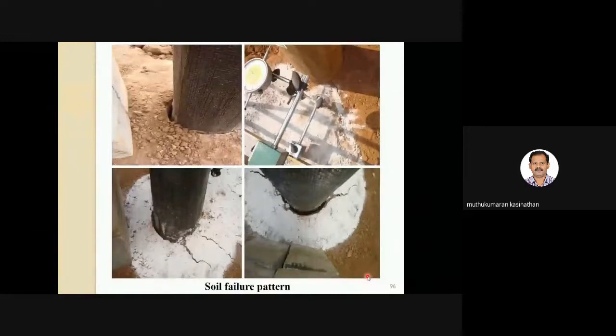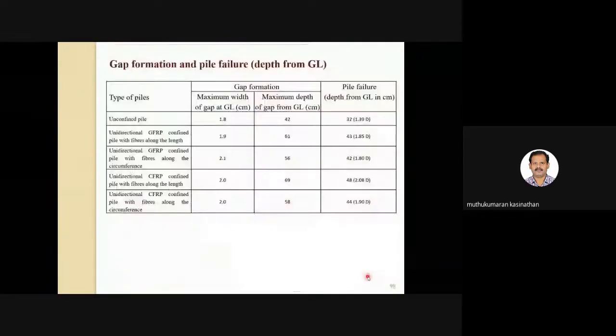So you can see here, all the failure patterns are measured, and the depth of fixity was again measured for all the cases. As you can see here, there is not much appreciable improvement in the depth of fixity, because the pile has already displaced a lot.